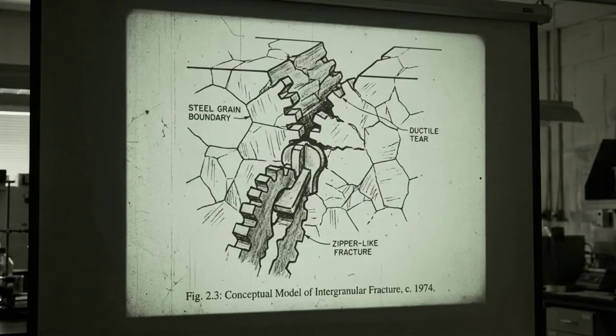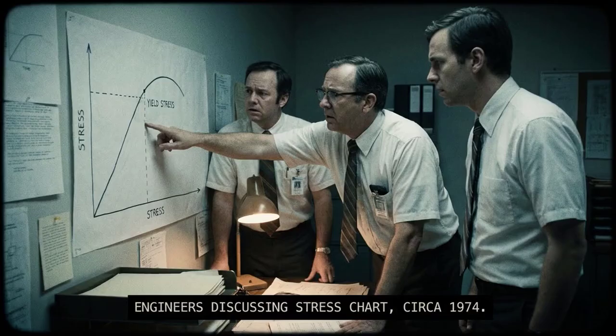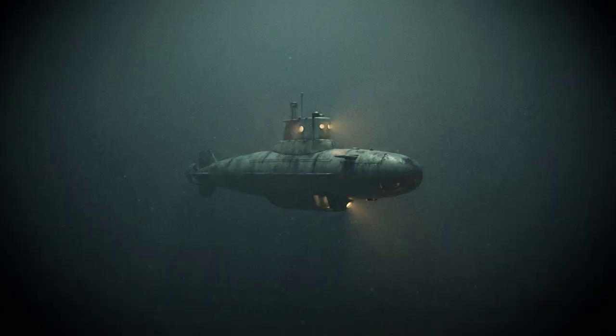Brittle fracture occurs when stress exceeds the material's ability to deform. Ductile steel bends before it breaks. Brittle steel snaps without warning. Corrosion removes ductility by creating microscopic cracks and voids in the steel's grain structure. When tension is applied, those cracks propagate rapidly, unzipping the material like a zipper. Once a crack starts, it accelerates. There is no gradual failure, no creaking or groaning. The hull will be intact one moment and torn apart the next.